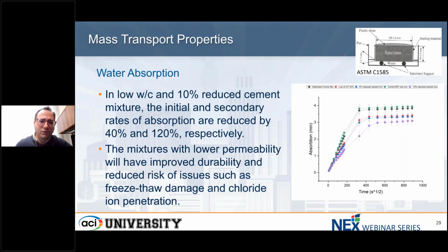The other mass transport criterion we looked at is water absorption, based on ASTM C1585, as shown in the top right image. After curing time, we seal the sample sides, and then from the bottom, we expose them to water for about 10 to 14 days. And these are the results you are seeing based on the absorption. Obviously, when we are lowering the water cement ratio, we should expect a lower absorption amount and lower absorption rate.